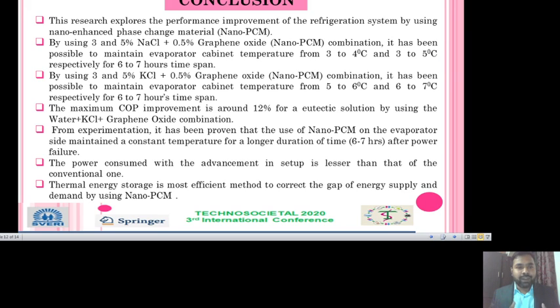By using 3% and 5% NaCl plus 0.5% graphene oxide, it has been possible to maintain the evaporator temperature at 3 to 4 degrees and 3 to 5 degrees respectively for a 6 to 7 hour time span. Similarly, with 3% and 5% KCl along with 0.5% graphene oxide nanoparticle, we kept the inside cabinet temperature at 5 to 6 and 6 to 7 degrees centigrade for 6 to 7 hours. So we can extend the cooling time of the refrigeration system, or cooling chamber, even though a power outage exists. From the experimentation, it has been proven that the use of Nano PCM on the evaporator side maintains a constant temperature for a longer duration, 6 to 7 hours, even though the power outage exists.